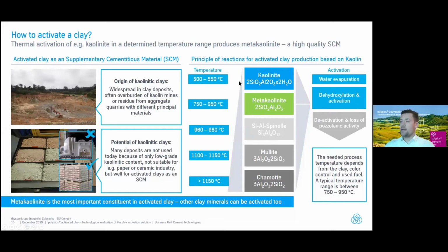So when activating clay, we are talking about, first of all, a water evaporation. And then we're talking about a dehydroxylation. This is what we're doing. And typical temperature ranges are then for the first step between 500 to 550 degrees C. And then the activation, meaning bringing the kaolinite to the metaphase, is done at a temperature between 750 and 950 degrees C. Also, this is then depending on the clay itself. So this we are evaluating in the lab before to find the perfect activation temperature for the best product quality.